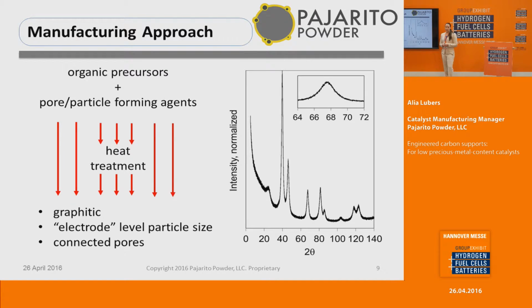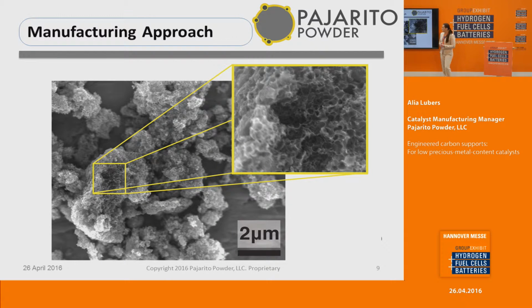How we produce these catalysts is by mixing organic precursors and pore formers, heat treating those, and we develop a very highly graphitic carbon. Our particle sizes are actually quite large for primary sizes. These are more along the sizes of secondary particles within the catalyst layer. However, we have really a very porous surface, and these pores are also interconnected. So being able to manipulate these properties, we can further optimize what our catalyst layer looks like and that three-phase boundary.